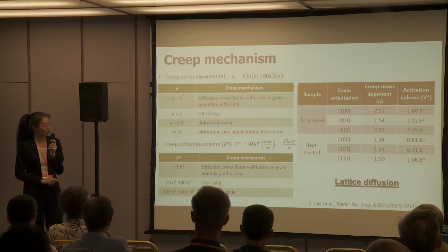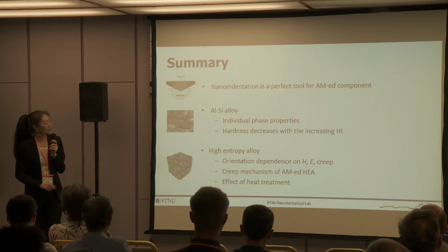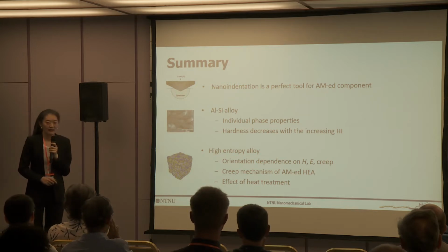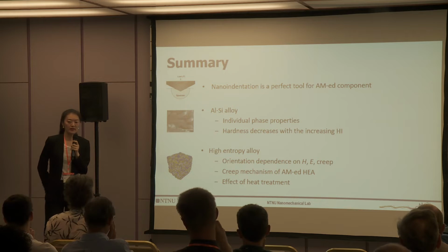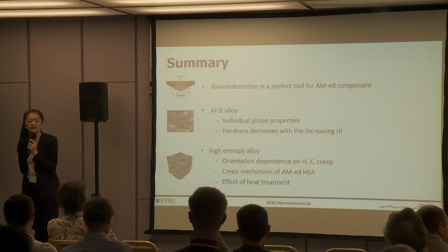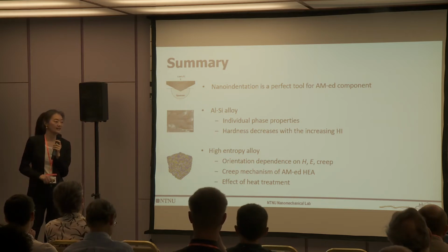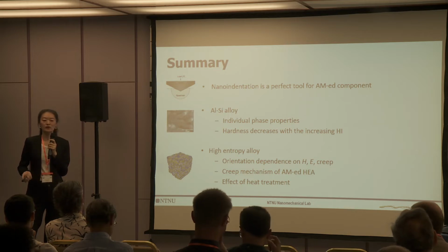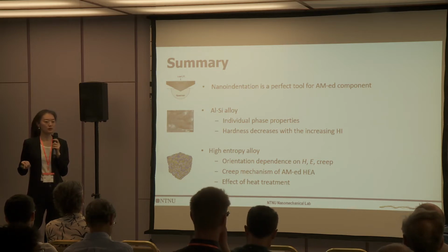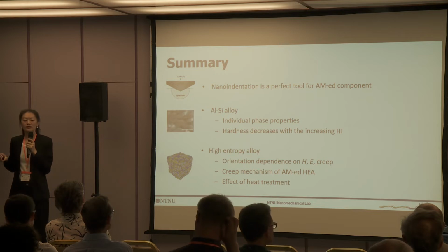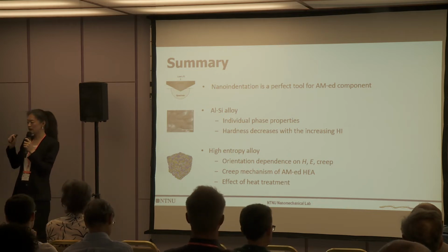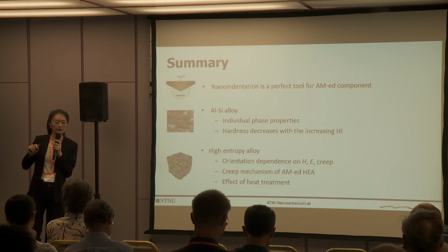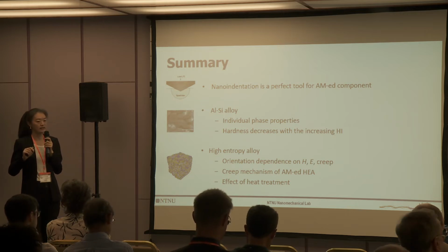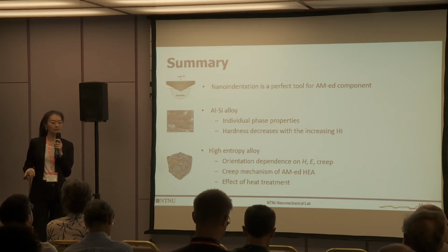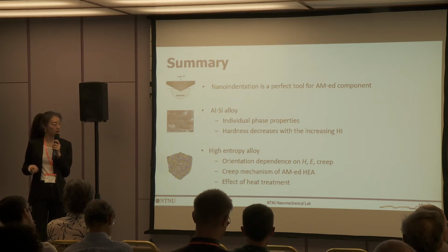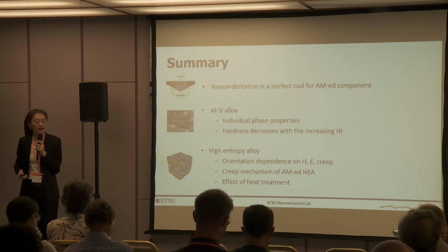Those were 2 examples of using nanoindentation to investigate how the processing parameters and also orientation-dependent behavior affect additive manufactured metal alloys. Then I come to my summary part. We see that the nature of the mechanical properties of additive manufactured components calls for nanomechanical testing, and nanoindentation provides a unique tool for this purpose. Nanoindentation gives point mechanical property mapping, which contributes to the process-structure-property relationship, and can further be used as a reference for the optimization and even the design of AM-ed materials.